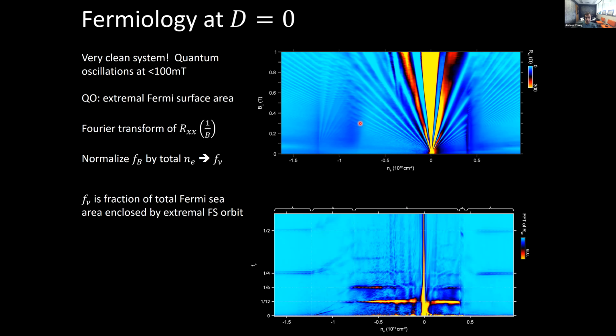Okay, so this is what it looks like, for example, at 0 displacement field. And I want you to focus in particular on what's going on here. At large density, we indeed see one strong peak that is at F nu of 1/4, and same thing for holes and electrons. That's exactly what I was describing before. You have 4 Fermi surfaces of equal area. Each of them is 1/4 of the total density, and that's everything that's going on.